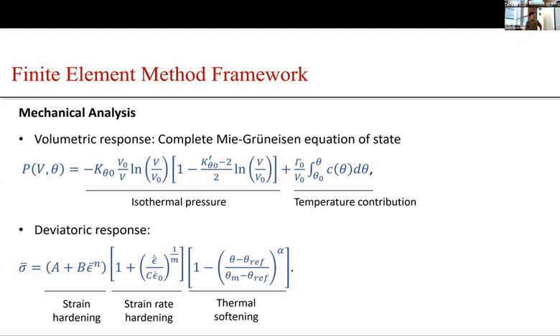I don't have enough time to present all the results, but if we look at the results from the simulation and the experimentally measured data using the impedance matching technique, the values are different, but not by too much. But perfectly plastic response compared to strain hardening responses are very drastically different types of mechanical response of the material that we're looking at. I don't know, in terms of putting the experimental results in comparison with the finite element results, would that introduce some errors when you compare?